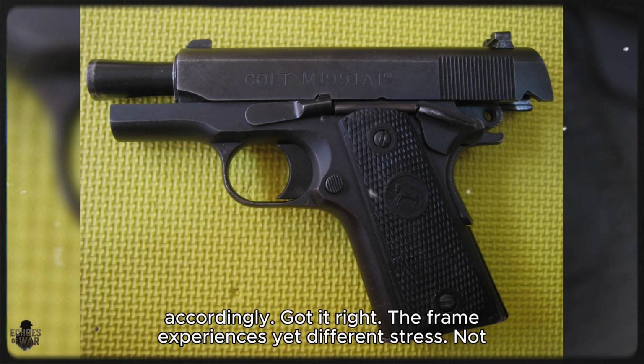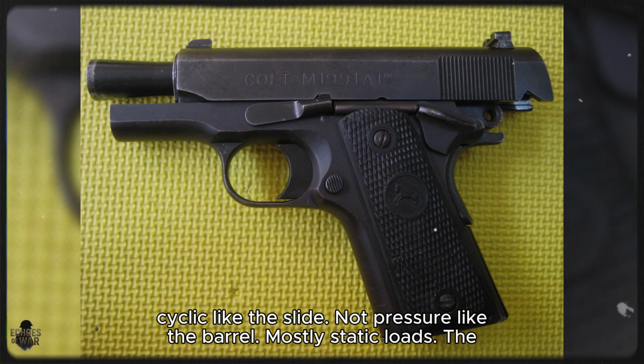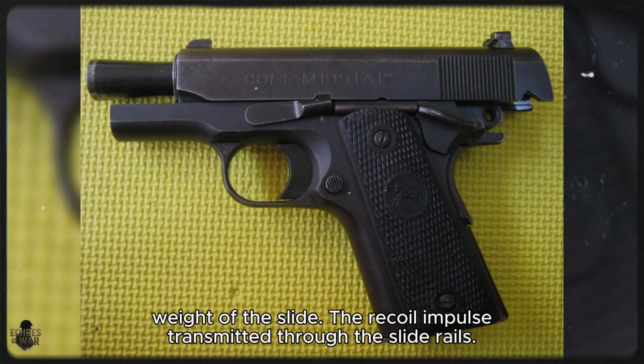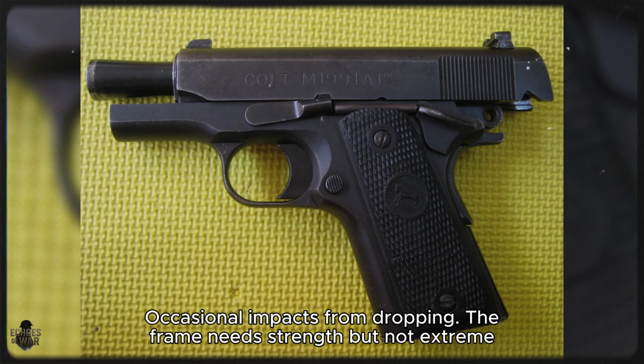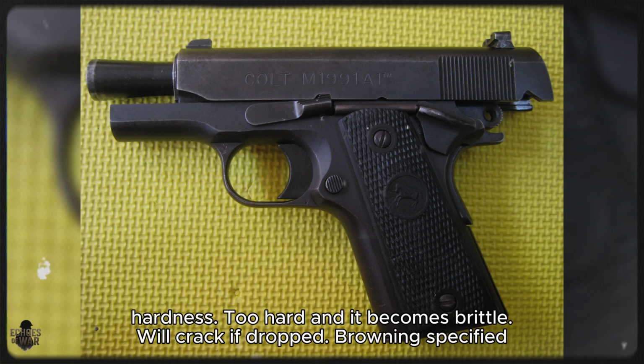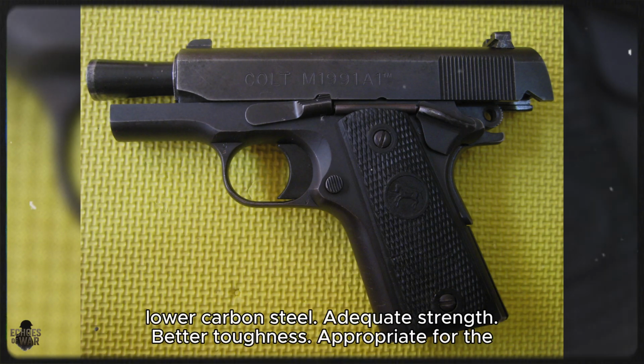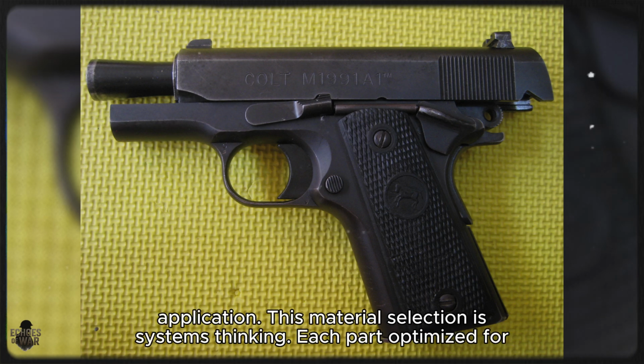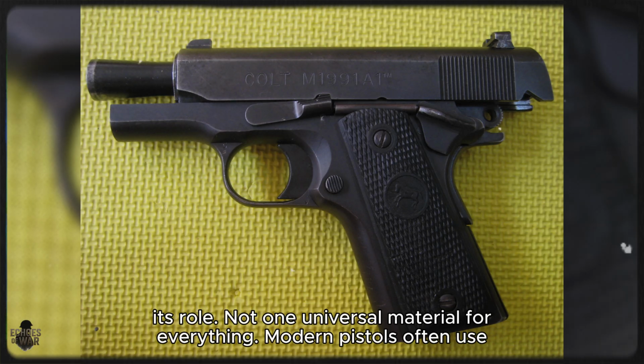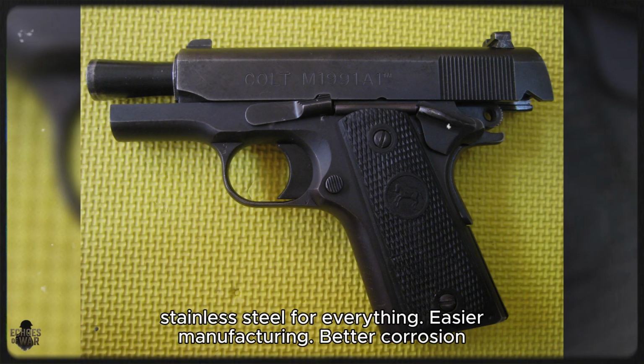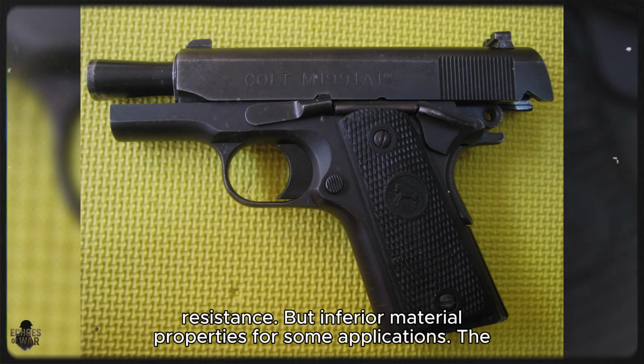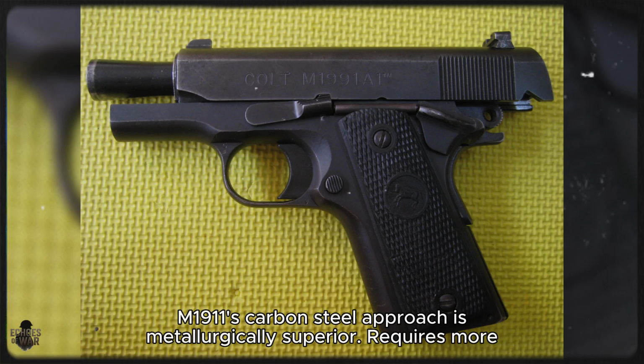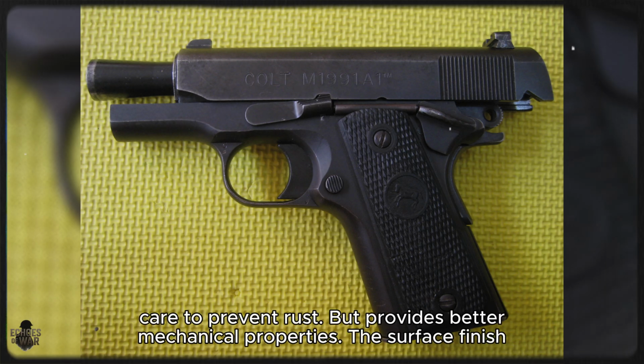The frame experiences yet different stress, not cyclic like the slide, not pressure like the barrel, mostly static loads, the weight of the slide, the recoil impulse transmitted through the slide rails, occasional impacts from dropping. The frame needs strength but not extreme hardness. Too hard and it becomes brittle. Will crack if dropped. Browning specified lower carbon steel, adequate strength, better toughness, appropriate for the application. This material selection is systems thinking, each part optimized for its role, not one universal material for everything. Modern pistols often use stainless steel for everything, easier manufacturing, better corrosion resistance, but inferior material properties for some applications. The M1911's carbon steel approach is metallurgically superior, requires more care to prevent rust, but provides better mechanical properties.